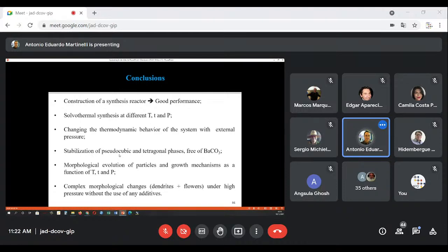Stabilization of pseudo-cubic and tetragonal phase. The tetragonal phase was the phase that we most observed. The peak shift that I showed you was characteristic of these early pseudo-cubic phases formed. The morphological evolution of particles and growth mechanism was explained as a function of temperature, time, and pressure, and we could obtain complex morphological changes such as dendrites growing into flowers in 2D and 3D under high pressure without the use of any special additives to result in these morphologies.